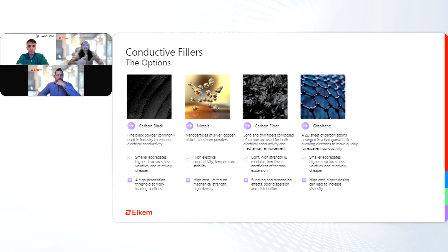Metals, such as your silver, copper, gold, nickel, aluminum, and so forth, are going to have great conductivity and be temperature resistant at the same time, but are often costly and limit the mechanical properties of your material. Third, you have carbon fibers. These are long, thin fibers composed of carbon that will increase conductivity and enhance mechanical reinforcement. They tend to be light, high strength, and high modulus. The negatives are that these will bundle and have poor dispersion and distribution.